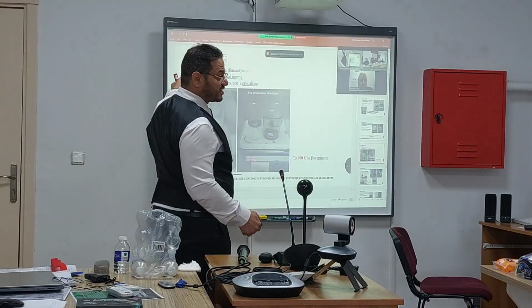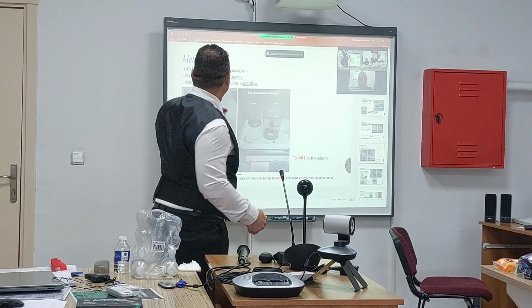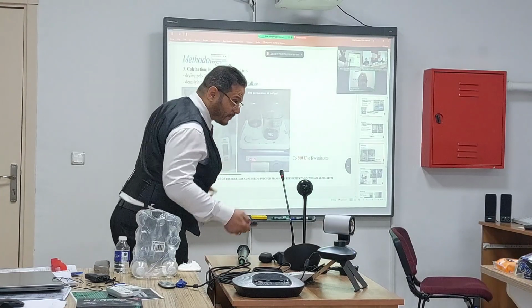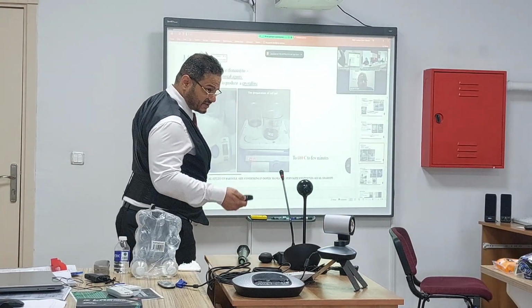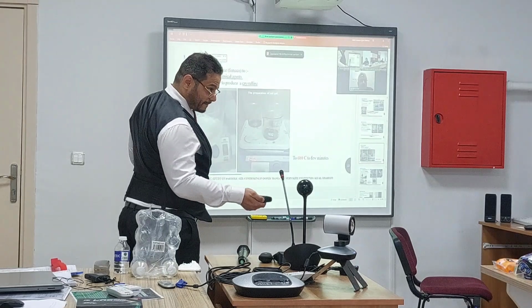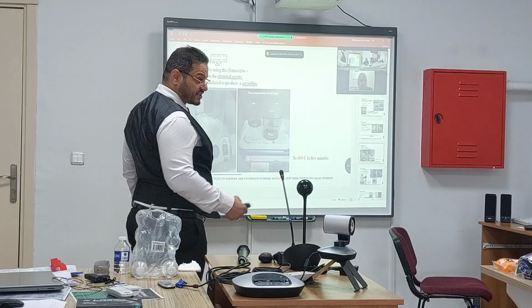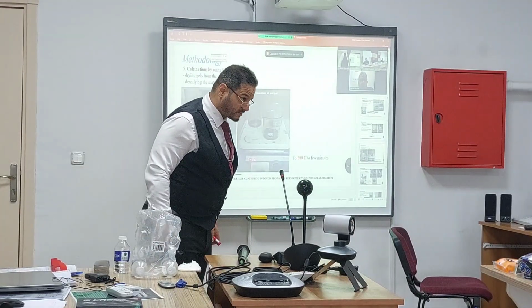Here is the calcination, using this furnace, not the bigger one. Calcination evaporates the organic elements, i.e. citric acid and ethylene glycol, by increasing the temperature more and more to reach 600 Celsius for a few minutes.